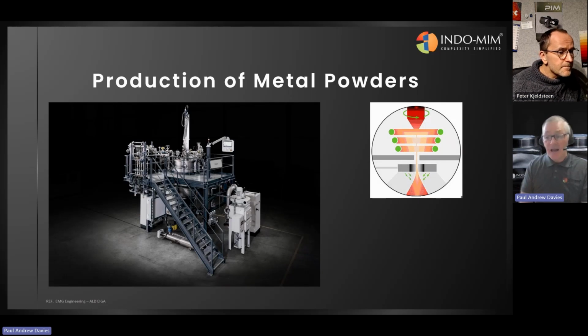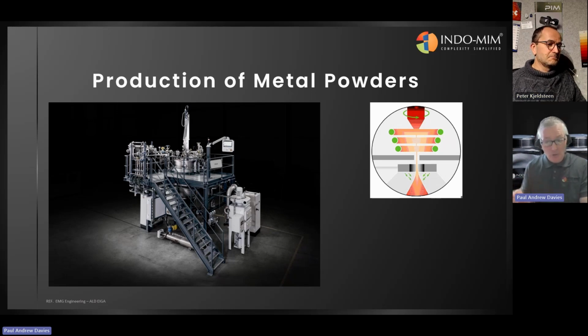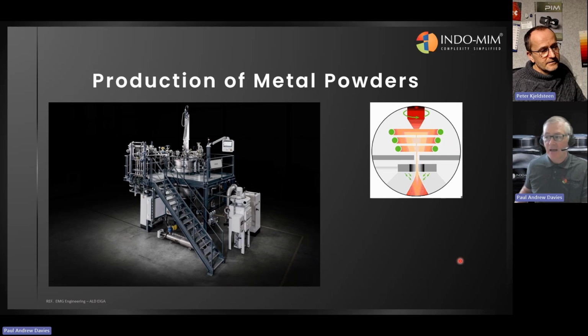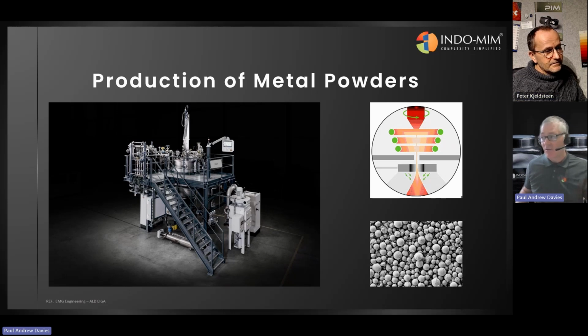This is actually an electrode induction melting gas atomization process. In this case, the bar comes down from the top and is melted in an induction coil. And that induction coil, interestingly, is copper, hollow because it's water cooled, and is actually 3D printed as well. So we're using 3D printing to make powders for 3D printing applications. Electrode inert gas atomizing tends to use free fall atomizers, especially for titanium alloys, so there's a refractory-free process in effect, again producing very beautiful spherical powders.